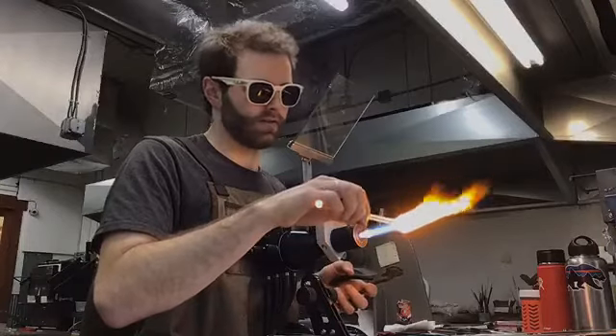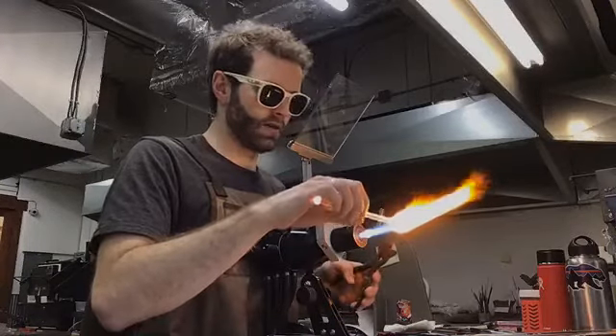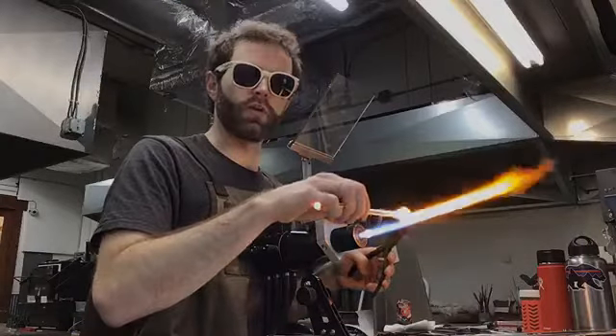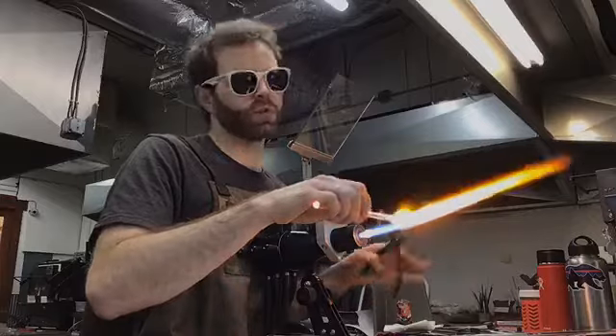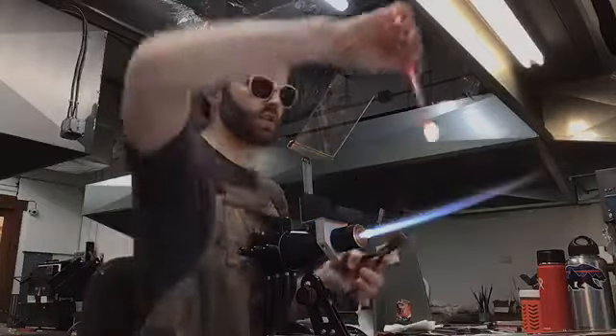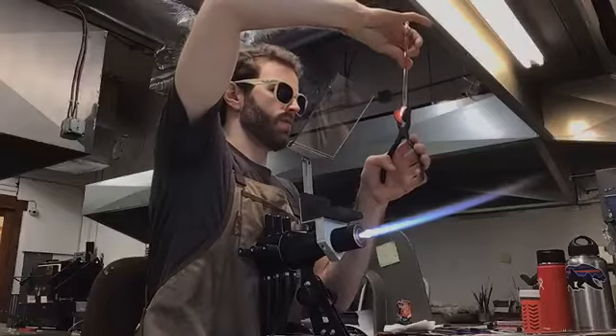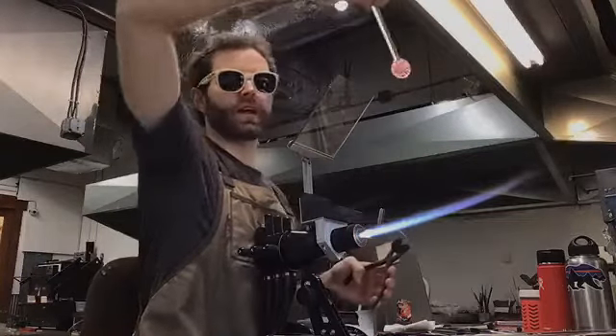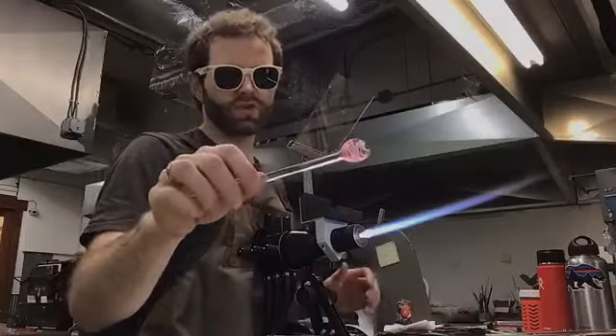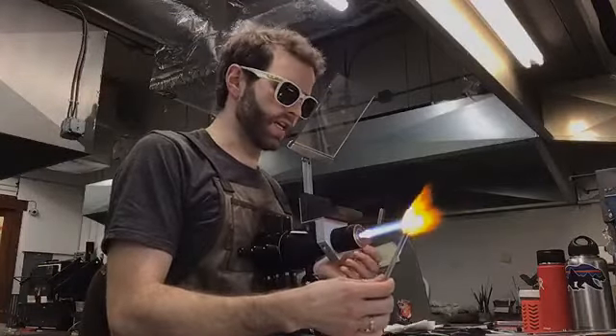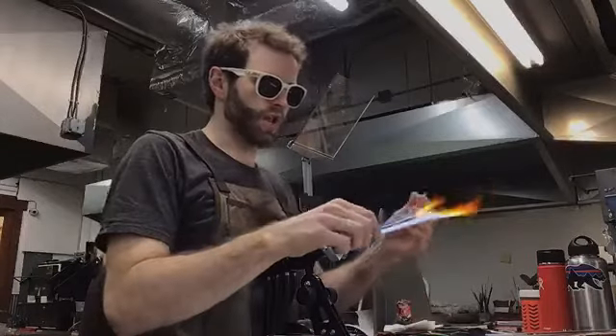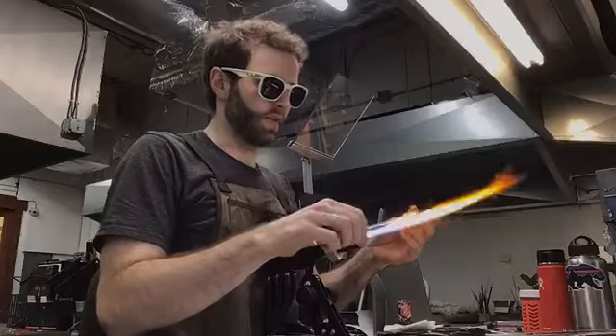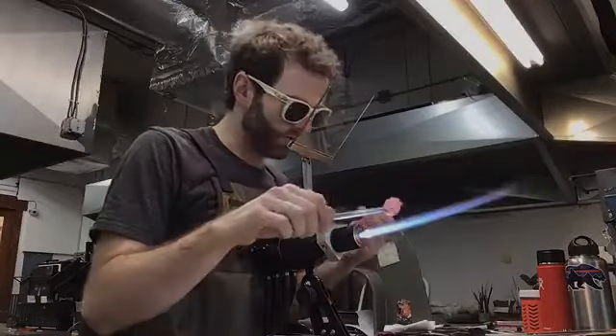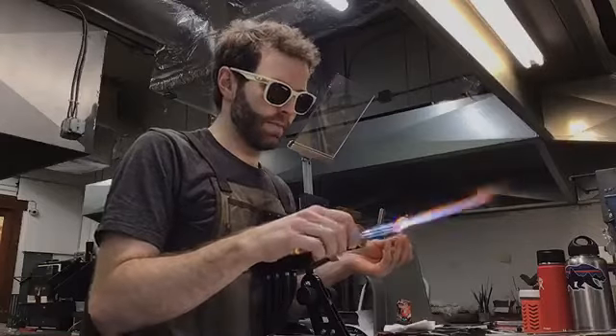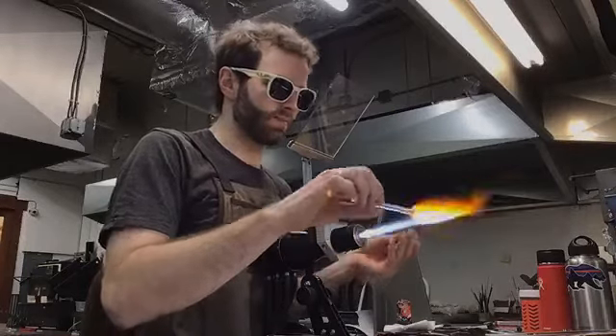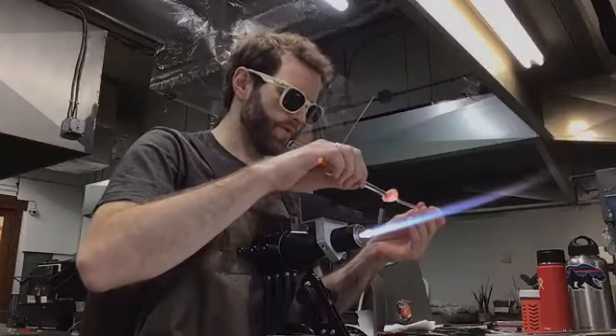Alright, so we got that nice and hot, melted all in. Really important anytime you're using the leaf mashers is that you want to go vertical with everything. If you hold things at an angle and go to squish it, things are going to get off center. So when I go to squish, you got to hold it straight upside down, rest it in that V, give it a good quick squeeze, and then let go. You don't ever want to squeeze for too long because you're robbing a ton of heat from that glass. You're thinning it out, and it's touching a cold metal tool. And if you leave it in that tool for longer than, I would say, 3 or 4 seconds, you'll start to crack the glass. So about 1 second is a good length of time to do that for.